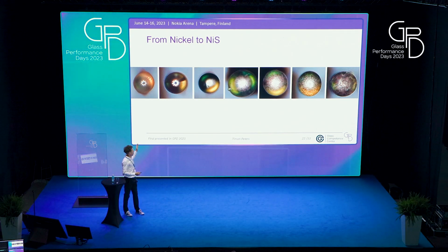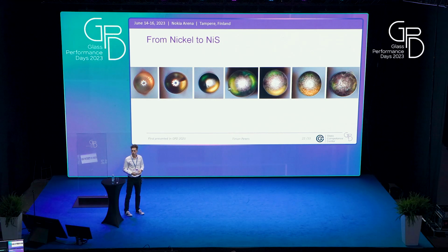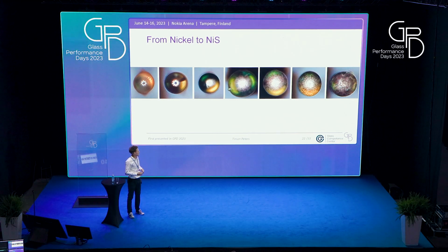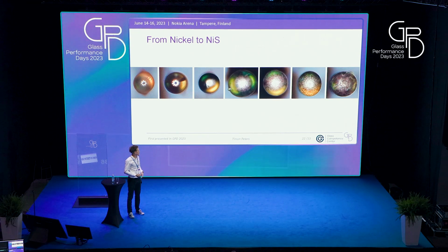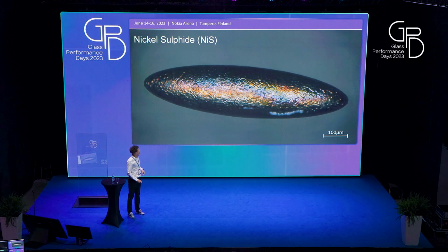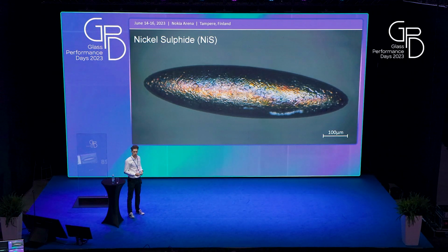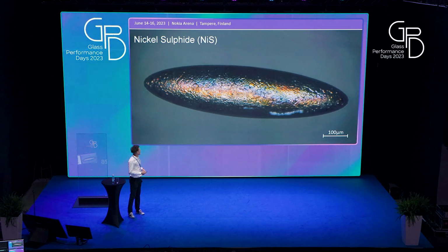So you can see the whole transition from the metal taking up sulfur and ending up as the mature nickel sulfide inclusion. And that's what we are getting to now. This is a nice picture of a very characteristic nickel sulfide inclusion.